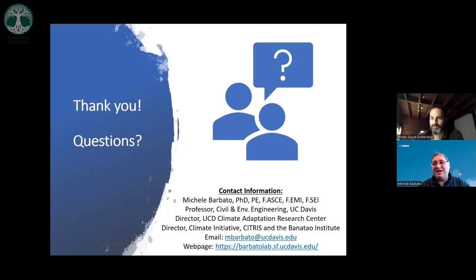If you want to increase the mechanical strength, the best approach is actually to increase the pressure used in the compression of the material instead of using cement, because if you start using 12% cement, now you're talking fundamentally about a CMU. A CMU typically has 15% cement. So can you still say, oh, we are so sustainable, when you are reducing only by 3% the amount of cement? I find it a little bit more difficult to justify.